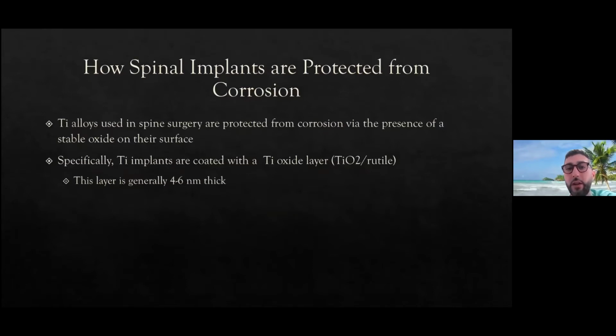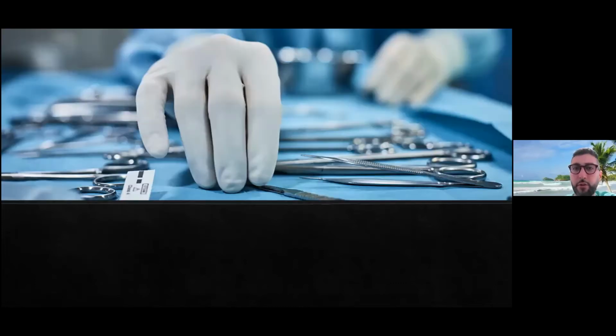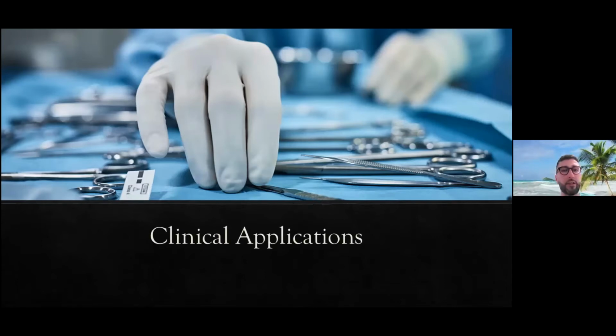Titanium alloys that we use most of the time are protected from corrosion with a coating. It's this titanium oxide layer. But again, that layer is about 4 to 6 nanometers thick. So again, when we manipulate rods, if there's a pseudoarthrosis and those rods are rubbing and that coating gets rubbed off, the potential for corrosion certainly exists. So that's kind of the basic definition stuff, and we can get on to the more interesting stuff, which is